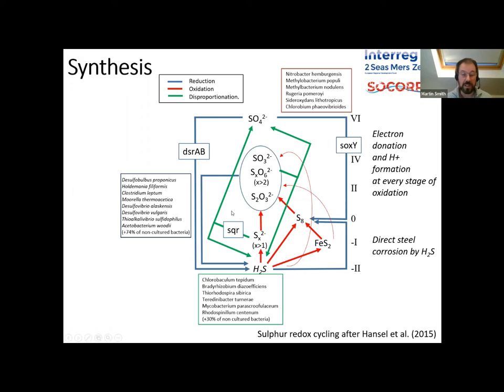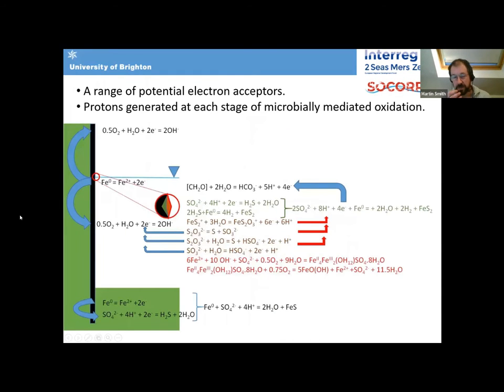We have organisms that take intermediate oxidation state sulfur compounds, so sulfite, thiosulfate, and use them as both electron donors and electron acceptors and produce hydrogen sulfide and sulfate. And we've got a huge number of bacteria in each case using those different metabolic pathways. So essentially, there's a huge amount of functional redundancy in these processes. We don't have to have exactly the same population in different sites to cause this same corrosion problem. And it's allowed us to put together this idea of what actually is going on.